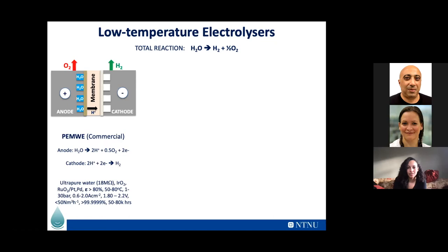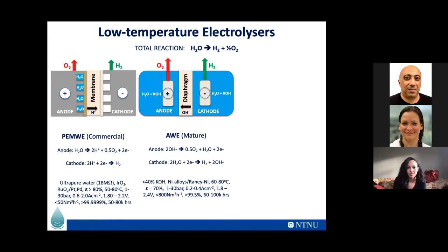Then you are looking at another technology which is more mature, the alkaline water electrolyzer or electrolysis, where you're actually using potassium hydroxide and some kind of nickel alloys or raney nickel, so non-PGM based, which is great. This technology has been around for many decades, many years. In fact, Norway was one of the precursors of that technology for the fertilizer industry.